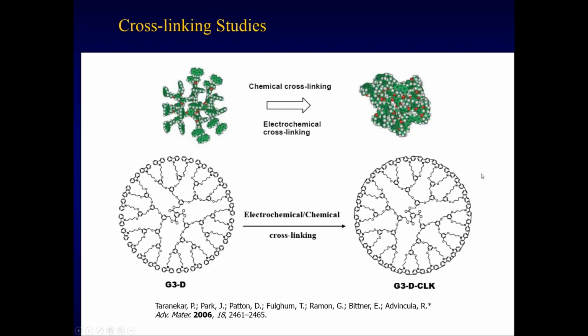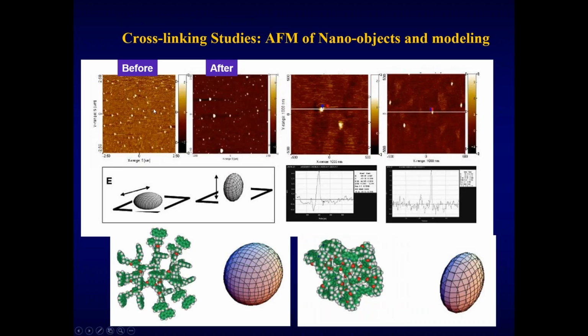electrochemical in situ cross-linking. So what we believe happened is that the dendrimers were able to polymerize intramolecularly, resulting in a more compact structure. So here is a relaxed flat structure before electropolymerization. Then after electropolymerization, it contracted to a lower hydrodynamic volume nano-object.